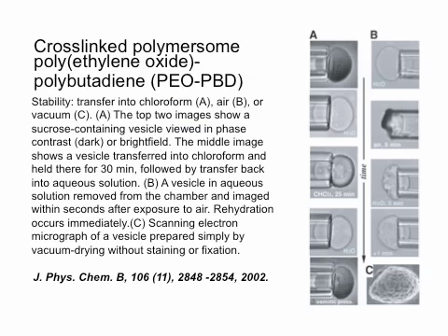Then the same thing applies, because obviously if you dilute this stuff, it disintegrates. So what you can do is cross-link the system, and you'll see very nicely in this picture that these things are then very robust. You have it in water, and then you can even dunk it in an organic solvent after it's been cross-linked, and it doesn't blow up, so it can withstand quite a big gradient in osmotic pressure, and then you can put it back in water and it rehydrates again. You can even let it dry out in air, and if you put it back in water, it forms back again. So it's quite a versatile little balloon that you've made, basically.